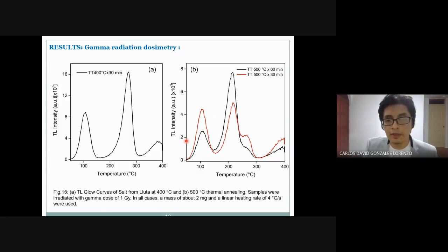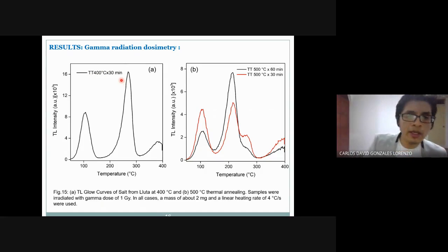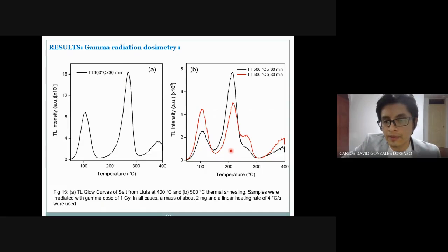Okay, so after we know the different TL glow curves obtained with previous thermal treatments, we decided to focus on this TL glow curve, which corresponds to the previous thermal treatment of 400 degrees for 30 minutes, as you can see here. However, what happens if the time increases? For this sample, we saw that with increasing time in thermal annealing, the TL intensity also increased.